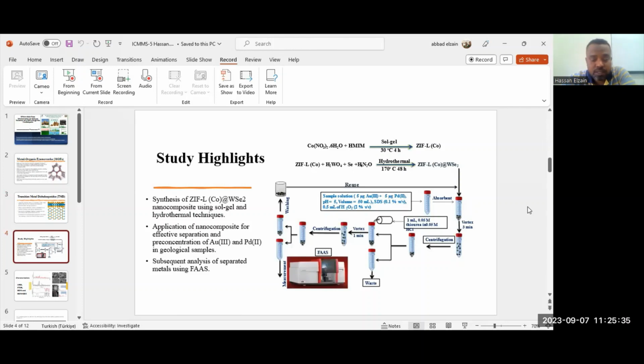Our study highlights, as you see on the right side, a graphical abstract of our method. The first process was synthesis of ZIF-L cobalt at tungsten selenide nanocomposite using sol-gel and hydrothermal techniques. Then application of the nanocomposite for effective separation and pre-concentration of arsenic and palladium in geological samples.